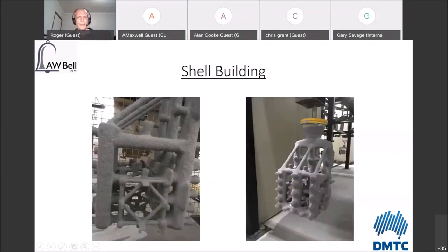So this is the shell being built, and it's going through the drying process here on the hangers while it's being dipped and dried. On the left-hand side, you can see it's building up. That's after probably 2 or 3 coats. On the right-hand side, getting close to the end of the process of putting on the backup coats on the ceramic shell. So this is starting to get close to the final stage of actually making it.